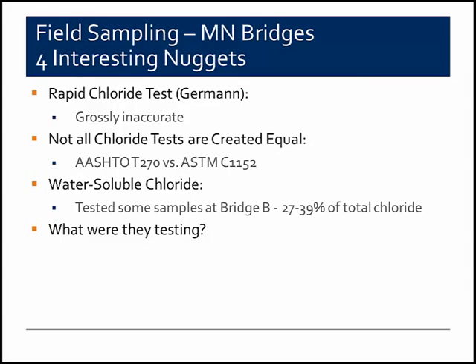So on somewhat of a side note, there were 4 things that I found interesting associated with the field sampling work that was done on the 3 bridges in Minnesota. The first is initially there was an effort to better define how many samples to take and where to take the samples, in other words, which grout lots to target. In the field, an initial sample was taken of a particular grout lot, and an instrument called the rapid chloride test was used. Essentially, the powder is mixed with a solution and shaken up for about 5 minutes, and a chloride content is measured.